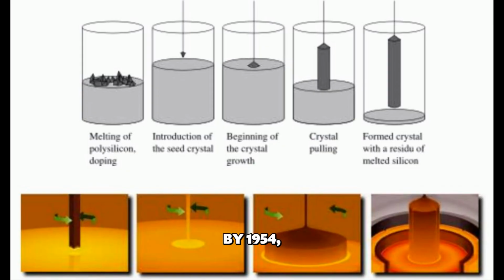By 1954, the semiconductor industry faced a fundamental choice. Researchers could continue refining germanium processes, hoping to find alloys or doping techniques that would extend the usable temperature range, or they could abandon a decade of germanium expertise and start over with silicon, an element that had a band gap of 1.12 electron volts, wide enough to prevent thermal runaway up to 300 degrees Fahrenheit.